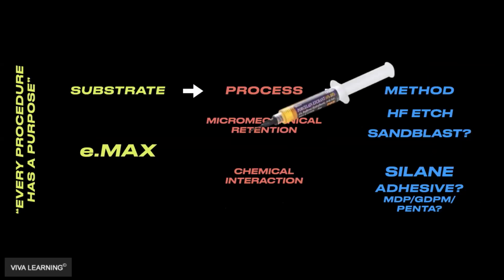So, hydrofluoric acid etch. Now, many people will say, hey, well, you're supposed to sandblast this? Now, Emax was made by Ivoclar, and in their instructions, they talk about not sandblasting lithium disilicate because you can introduce internal fractures. Now, I've been practicing for 16 years. Do I know if sandblasting has contributed to the weakening of lithium disilicate? No. But have I had lithium silicates break? Yes. It could be from sandblasting? Maybe. I think it's probably more to the prep design more than anything else. But what are you really accomplishing with sandblasting more than a hydrofluoric acid etching? Not really a whole lot.